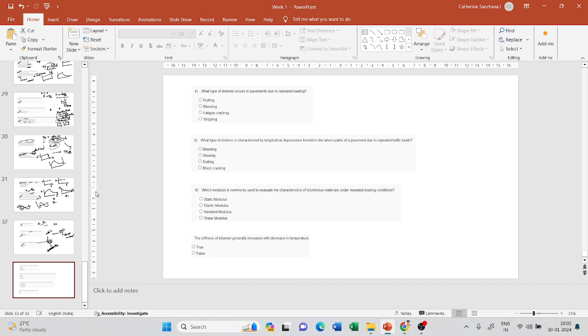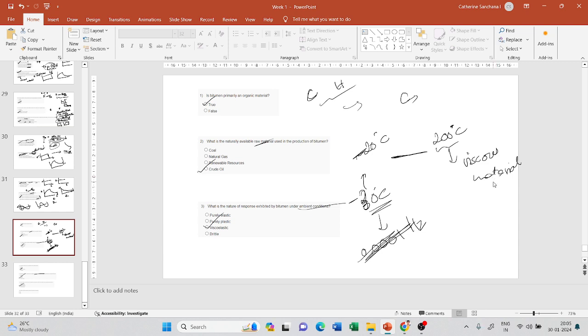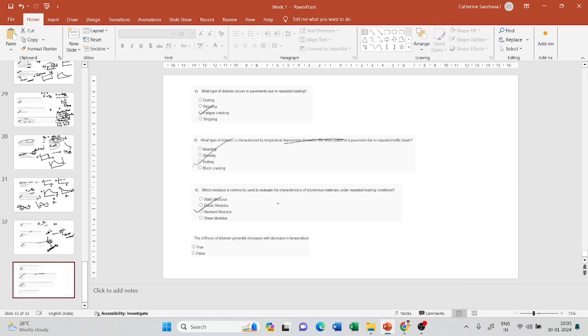Moving on to the final set of slides. What type of distress occurs in pavement due to repeated loading? We saw this a few questions back. It is fatigue cracking. And what type of distress is characterized by longitudinal depressions formed in the wheel paths of the pavement? That also we saw. It is rutting, right? And this question we already saw. It is resilient modulus. And the stiffness of bitumen generally increases with decrease in temperature. What we saw in the earlier slide, at high temperatures it has a high possibility of behaving as a viscous material, which means its stiffness will be very less. At low temperatures, it will behave like an elastic material, which means its stiffness will be very high. So its response depends on temperature, and stiffness increases with decrease in temperature. So it is true.